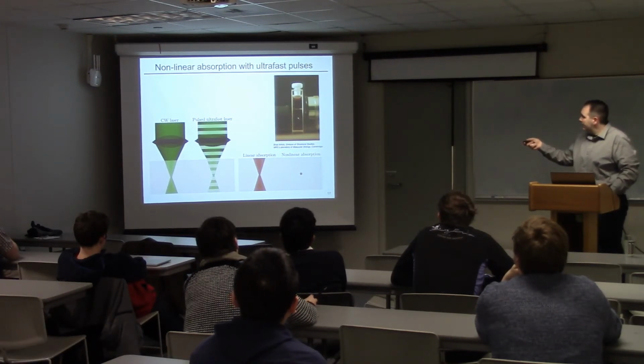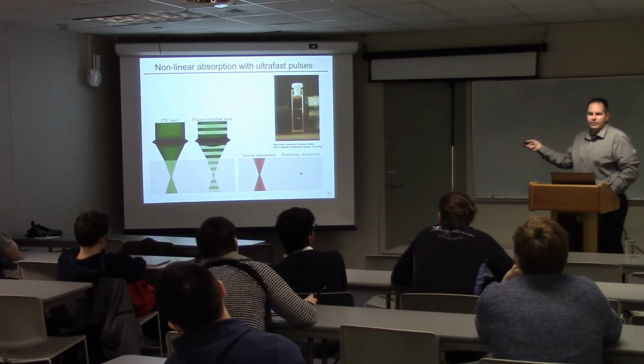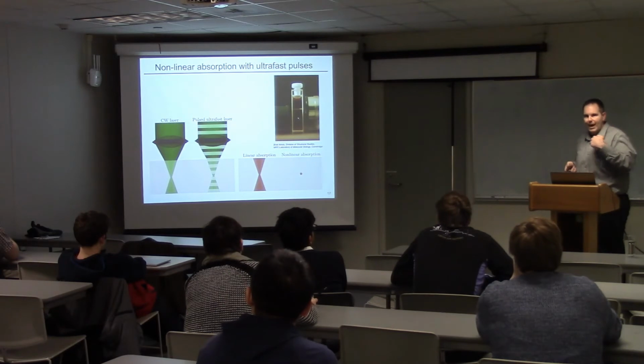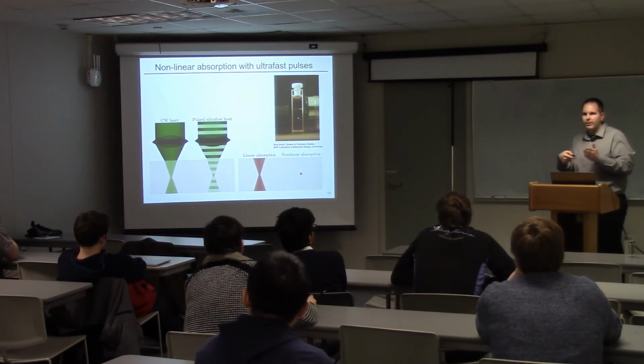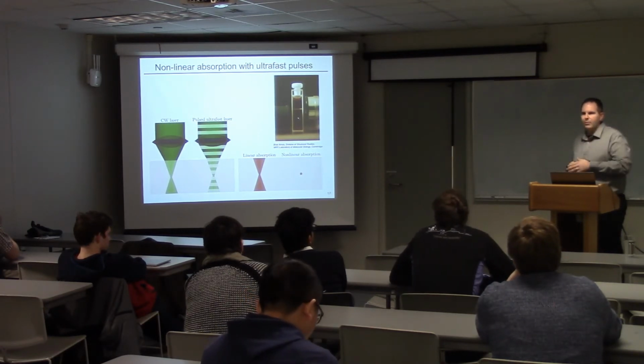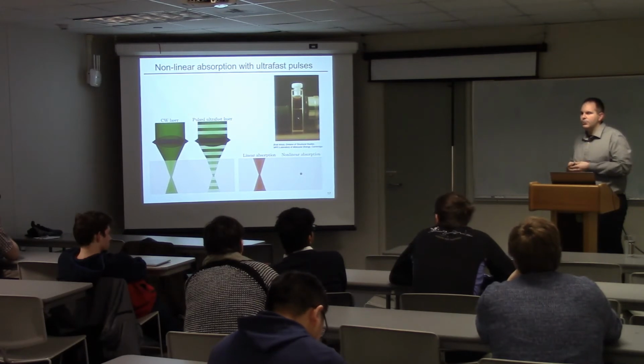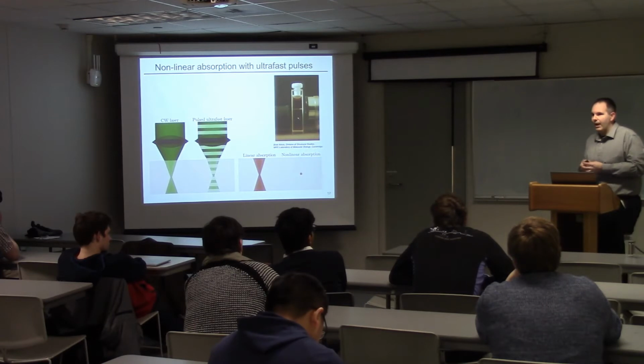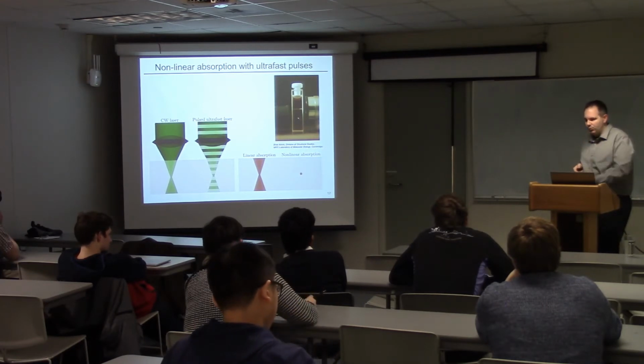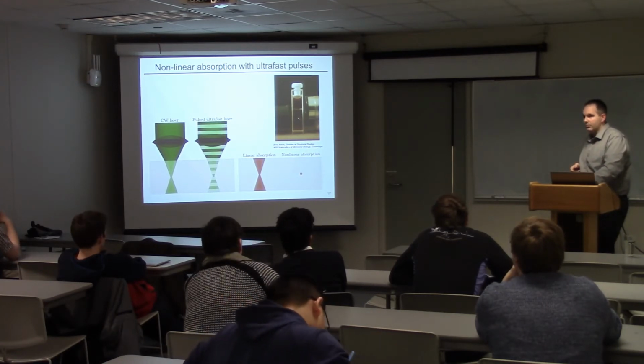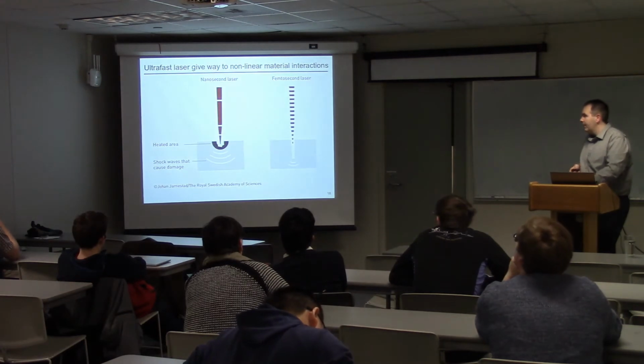And basically, what to note here is that they're using a wavelength that is transparent, that would normally pass completely through. Like this red laser pointer here would pass through the window panes at the back uninterrupted. But if we focus it and make it an ultrafast laser pulse with red, you can actually make that glass absorb the red light. And there are some really cool things that you can do with that.